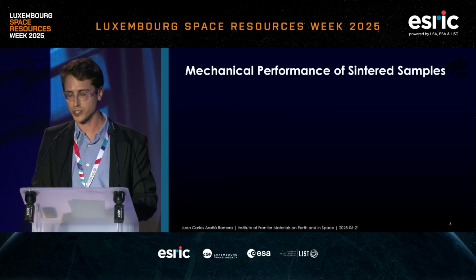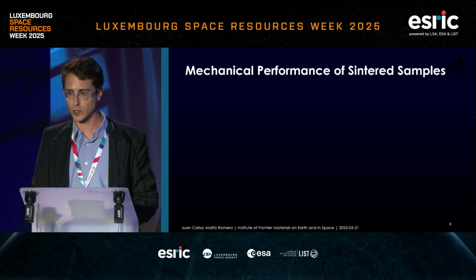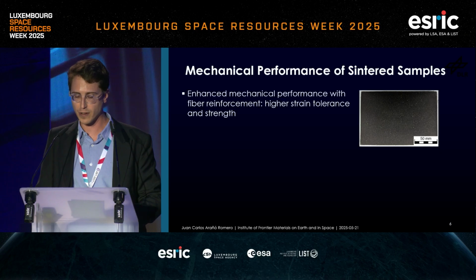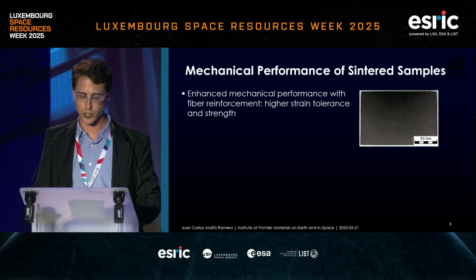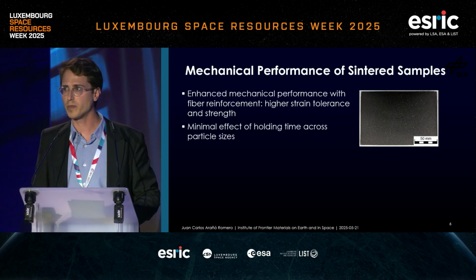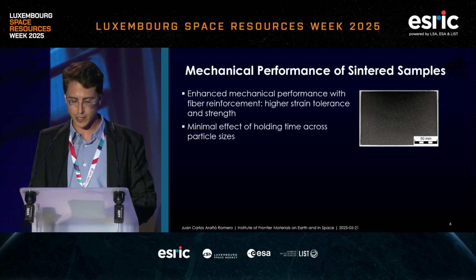The mechanical results of our sintered samples will be described, and how the fiber reinforcements improve them. First, with fibers, we saw improved performance: the samples tolerated more strain and reached a higher strength in comparison with the samples without fiber reinforcement. Interestingly, the holding time during the sintering, the thermal treatment, didn't have much effect on the performance across different particle sizes.